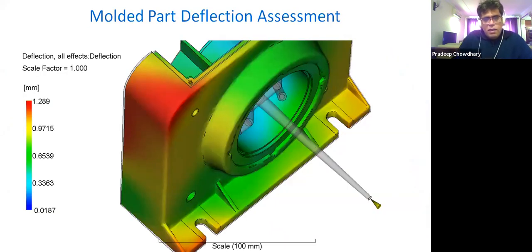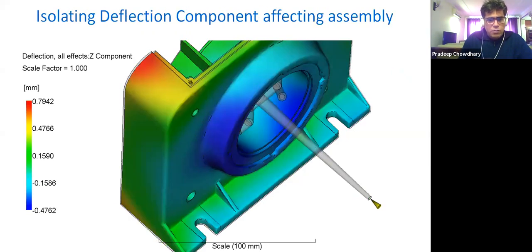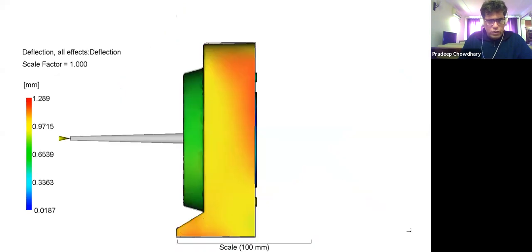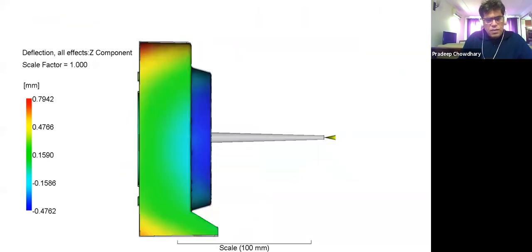Then came some results. With this semi-crystalline material, even with very balanced center fed gating, we got extremely high warpage. Deformation came, and the variation of that deformation was a bigger issue because on some corners, the fiber orientations were one way, and on the other corners, different, and due to volumetric shrinkage, one could see that this deformation is going to have a different effect on different areas of the part. Tried with a couple of different materials, but we could not contain the deformation to less than 0.8 in the direction of our assembly, which was a huge concern for a part that required extremely high dimensional accuracy at the time of assembly.